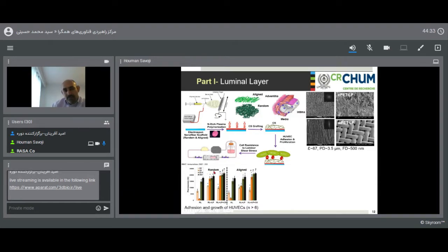And this was similar for random and aligned structures. So the cells also responded to the structure. On the aligned fibers, they really spread towards the direction of the fibers, and on the random structures, they are randomly oriented or spread. So the cells are happy. They form focal adhesions on the material, which means that they're attached, and they also communicate with each other by expressing the biomarkers that we show here in white.